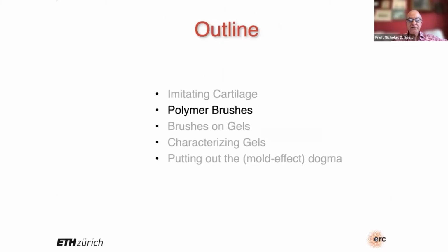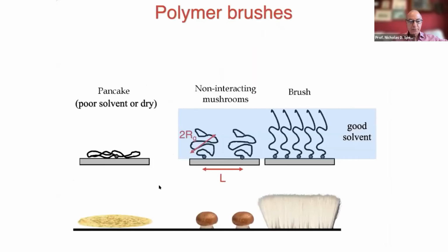Now, polymer brushes are an important part of the whole project and something we've been working on for the last 20 years or so. And just a very quick introduction to polymer brushes. They involve anchoring polymers at one end to a surface and putting them under a good solvent. If they're in a poor solvent or if they're dry, then they crash down onto the surface, and we call this the pancake configuration. If they're hooked onto the surface and they're widely spaced, we call this the mushroom configuration, because they're partly looking like the way they do in solution in the good solvent, but they're restricted in motion because of the anchoring. Just see if I can get my spotlight back.